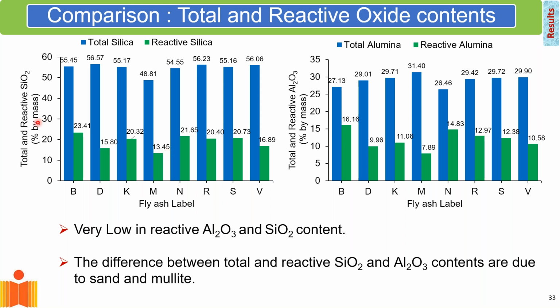And also, if you look at the reactive silica content, there's a large variation. And this is what contributes to the very large variation that we see in the strength and even other properties when we start using fly ash. So now this actually tells us that we do have fly ashes which have higher reactive silica in them, like this fly ash B, and we have fly ashes that have very low silica content in them, which is 13%.